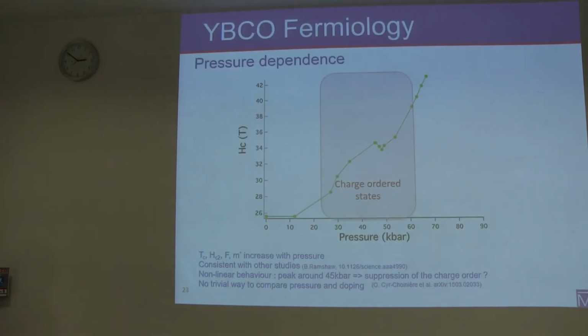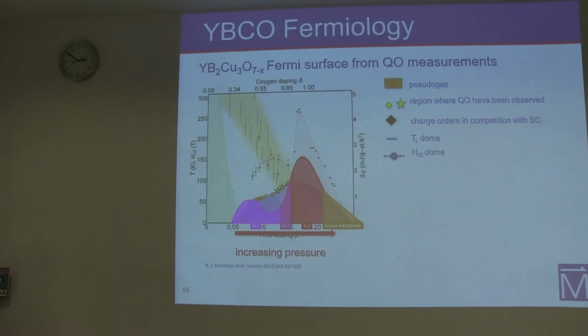I'm not quite sure I understand. When you plot HC2, it's almost one-to-one with TC, at least in the underdoped area. If TC is 50 Kelvin, HC2 is about 50 or 60 Tesla in this doping plane. But that would be a very small region, right? Because here the critical field decreases a lot. Sure, that's true just for that point here. But at least for the pressure, they are very different, almost double. So for doping, if we have about 50 Tesla, it's about 50 Kelvin.